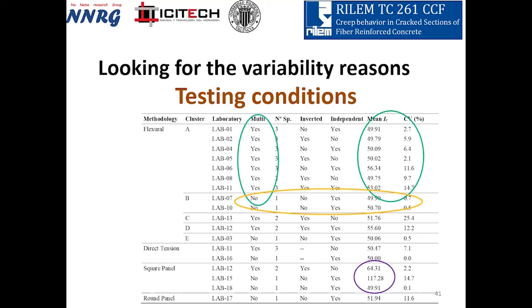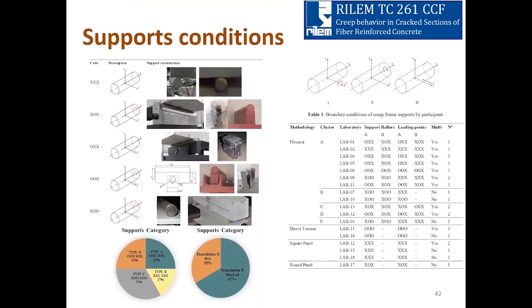Of course, in round panel, we have only one laboratory and direct tension is feasible, but the number of specimens was very low and the number of laboratories is also low. Then it's difficult to guarantee a methodology to be supported by the standard. The support conditions were also difficult to understand, but I think they are less important as an influence, but the details must be coordinated.